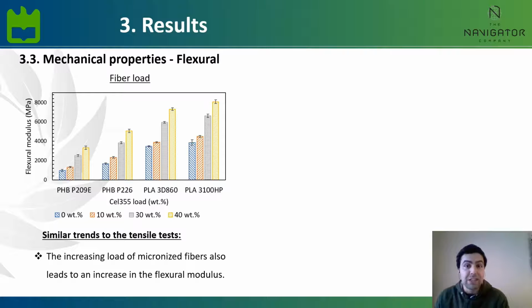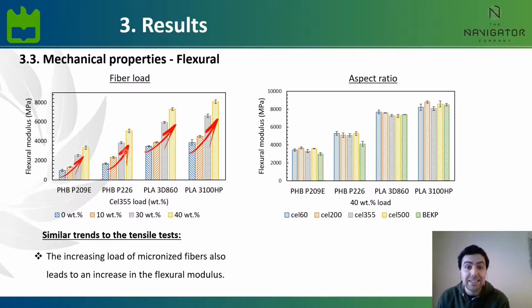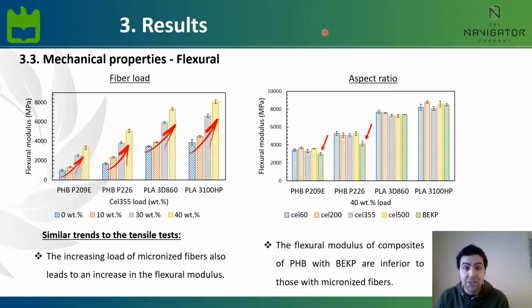The results for the flexural properties in the 3-point bend test are in good agreement with the results of the tensile properties. And that means that increasing the fiber load leads to an increase in the flexural modulus, as you can see on the graphic on the left, and the aspect ratio of the micronized fibers had little influence, as we can see in the graphic on the right. Nonetheless, we can see again the inferior flexural modulus of composites of PHB with bleach eucalyptus kraft pulp compared to the composites with the micronized fibers.